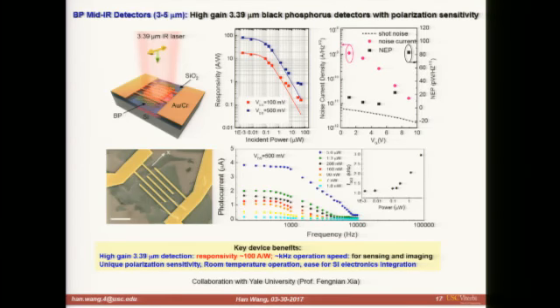In this work, we demonstrated a BP detector that can respond to 3.39 micron wavelength lasers, and we see a responsivity of 100 amps per watt. This is very decent performance at this wavelength at room temperature.